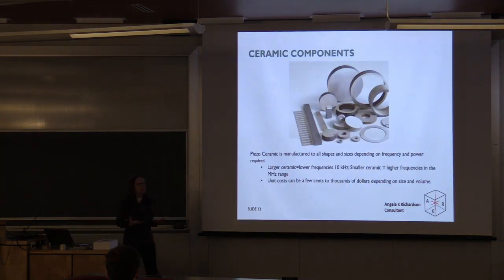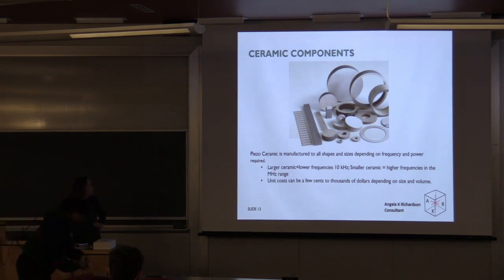Now, those piezoceramics that are in all of those devices, they come in all shapes and sizes. And Lindsay was gracious enough to bring some ceramic here. So whether it's at the end of the class or you want to just pass these around, I would imagine these are all lead zirconate titanate, so fairly heavy compositions. But the larger the ceramic, the lower the frequency, somewhere in the 10 kilohertz range, and the higher frequencies typically in the 5 to 10 megahertz range.